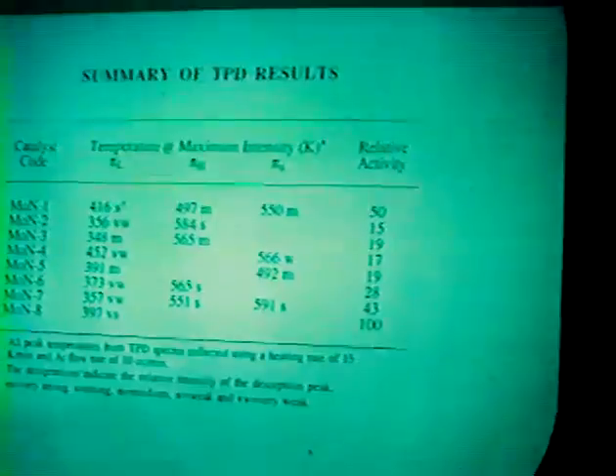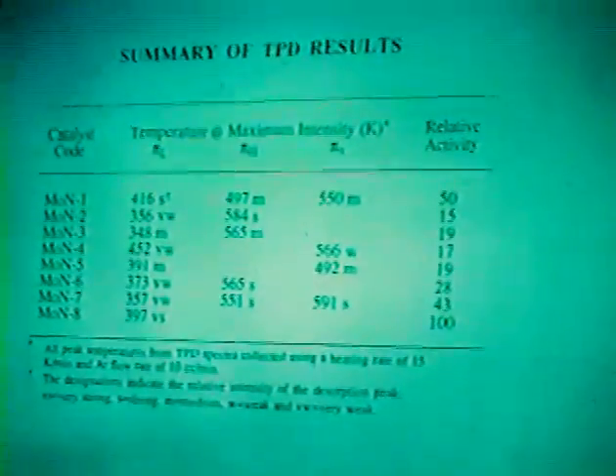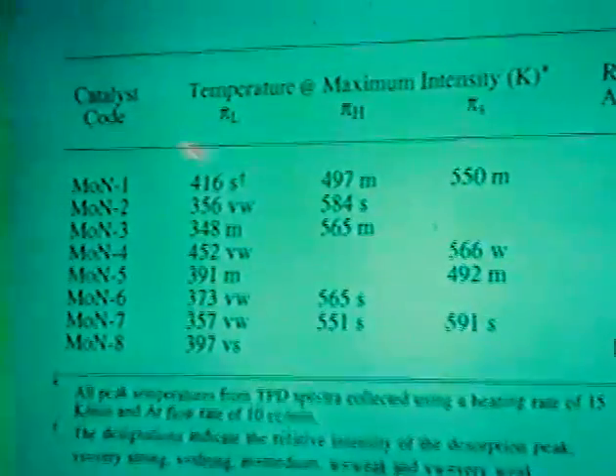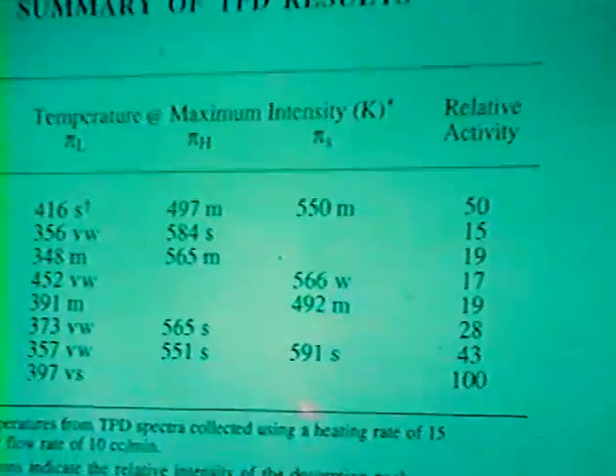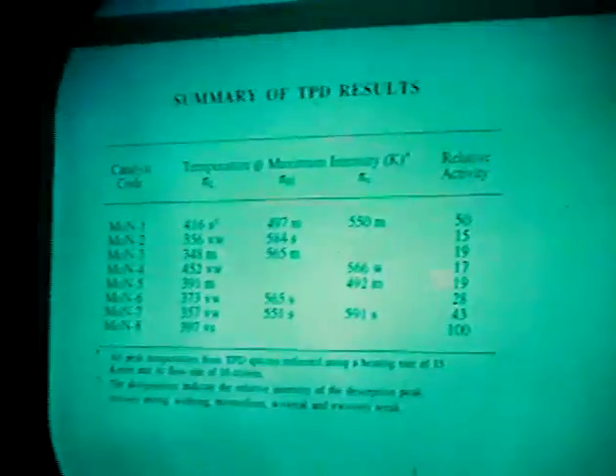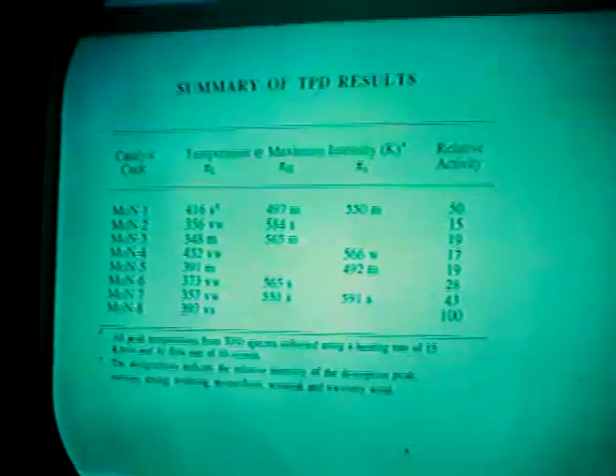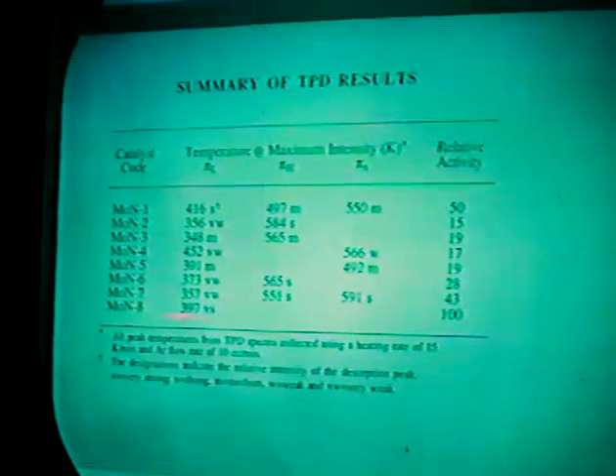The sample I just showed you was sample number 1, a kind of modest surface area material. This is sample number 8, which, as you'll remember, had the lowest surface area. It also had the highest intrinsic activity. We notice that there is a very marked difference between the TPD spectrum for the higher surface area materials and that of this low surface area material. We were struck by the differences, and as I'll show you on the summary slide, sample number 8 was the only one that gave rise to a single peak in the TPD spectrum.